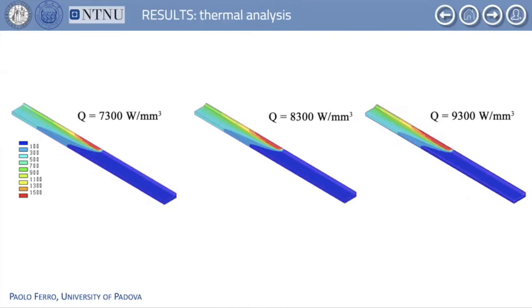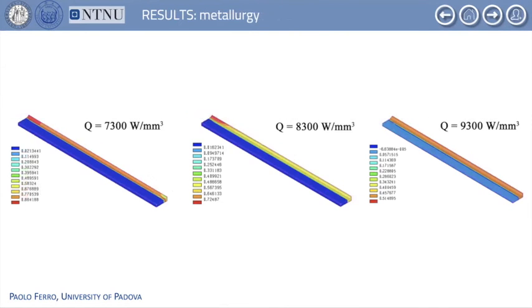This figure shows the fusion zone produced by the heat source during welding as a function of power input. It is important to observe that the bead geometry was adopted according to the analyzed process parameters. The higher the heat input, the larger the weld bead. As a matter of fact, the bead geometry varies with process parameters, so it was necessary to modify manually the geometry of the fusion zone, since fluid dynamic phenomena are not simulated in the computational welding mechanics approach.